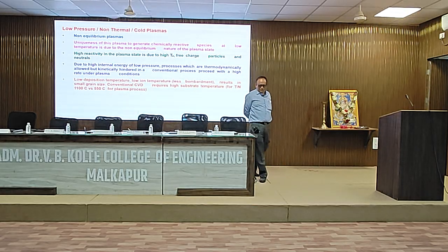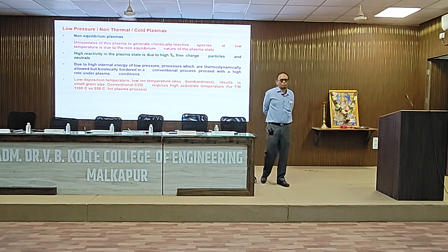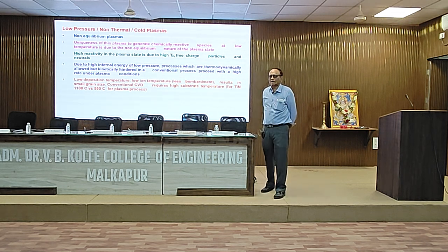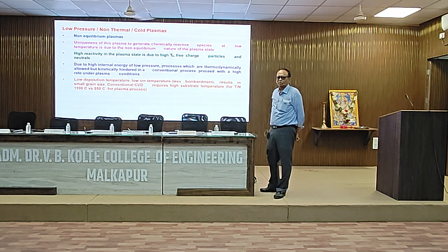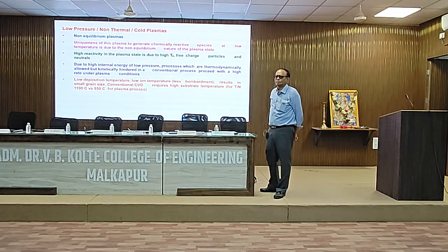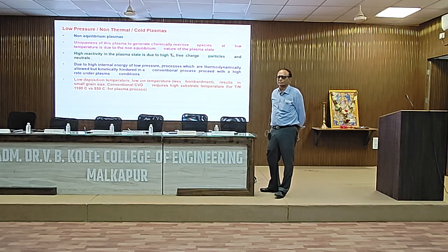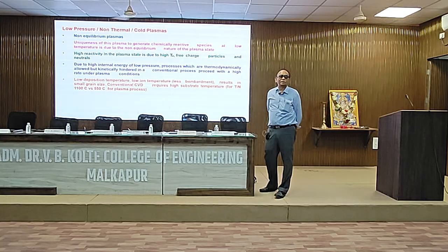It is creating very active ions of titanium, nitrogen and all these things, and that has ended up giving me a reduction in the process temperature to 550 degrees centigrade.